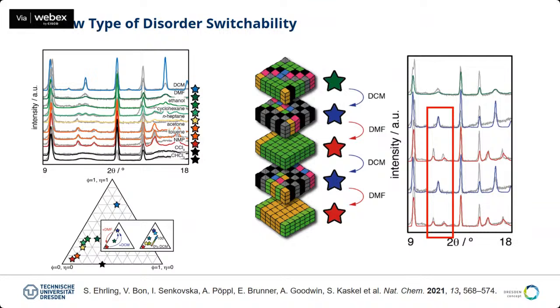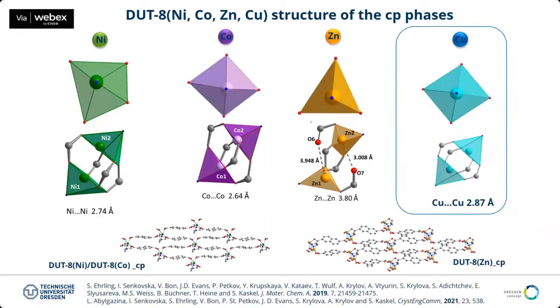This took us a long time, and maybe this is also an interesting take-home message: sometimes it's worth digging deeper to find out what is really happening in this kind of structure. Now, let's look a little bit more closely at the contracted phases. I told you that the nickel cluster is very much distorted, but the distortion is even heavier when you go to the cobalt and to the zinc cluster.